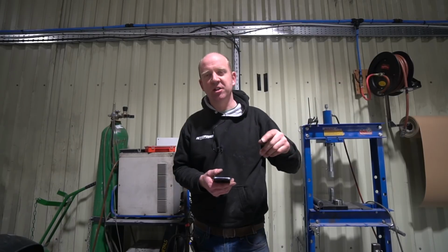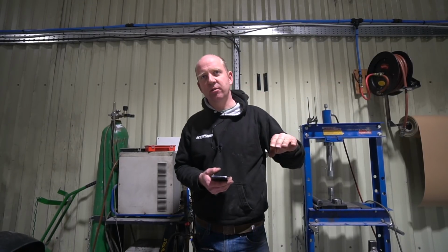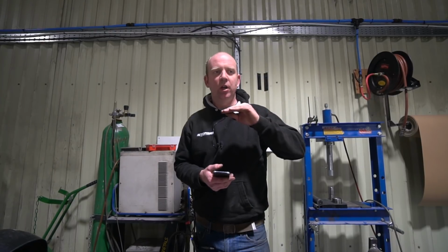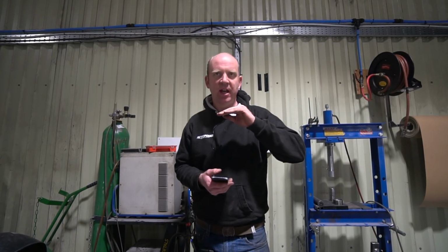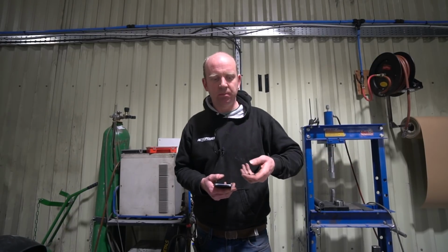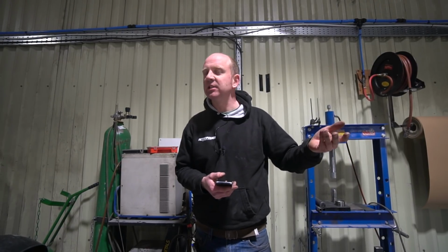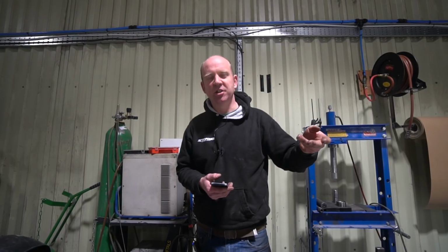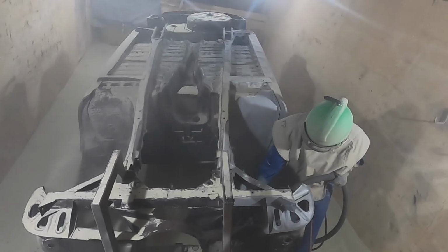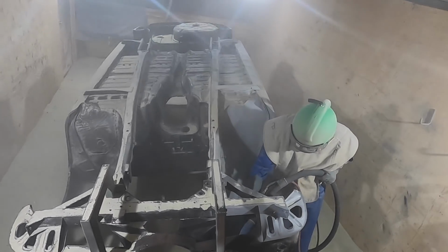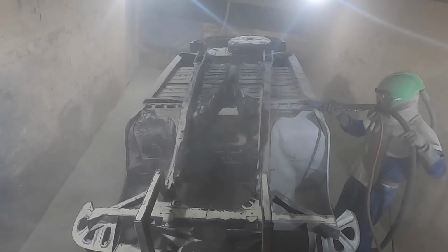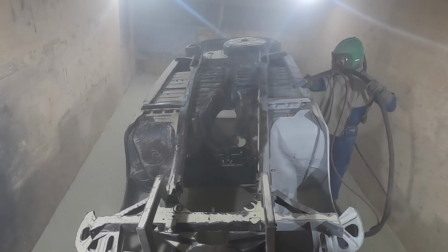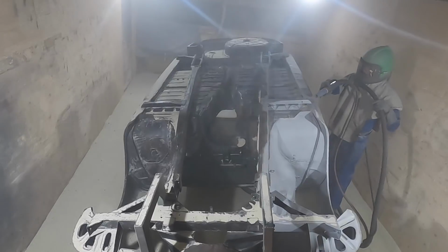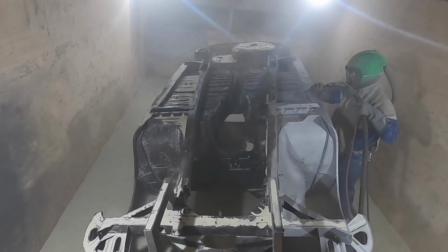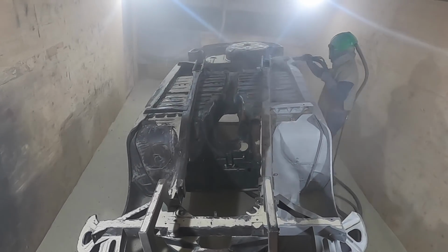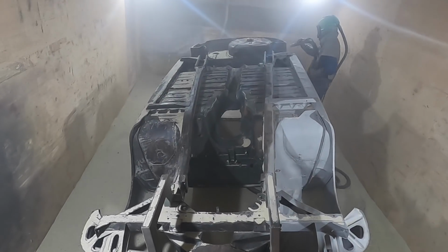off the floor, we run it through the vibrating screen deck, and that screens out the very fine material, which we discard, that goes to landfill. Then we screen out the larger particles, bits of paint and other debris and lumps that could block the blaster. They go to landfill, and then we screen out the middle fraction of the correct size grit, and we then remix that with new grit so that it gives us a spectrum of particle sizes, so that it then has a very good cleaning action. So that's what we do in terms of grit recycling. Yes, we do. Some goes to landfill.